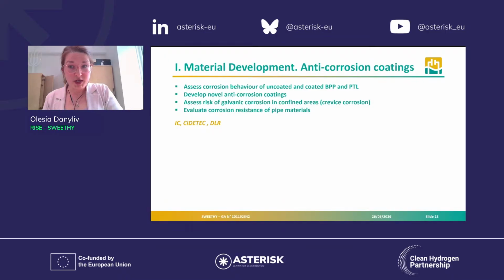To finish describing the material development within SWEETHY, I refer to the anti-corrosion coatings that we are doing in the project. So within development of anti-corrosion coatings, we are looking at the corrosion behavior of uncoated and coated bipolar plates and porous transport layers. We are developing the novel anti-corrosion coatings. We are assessing the risk of galvanic corrosion in confined areas, and we are also looking at the corrosion resistance